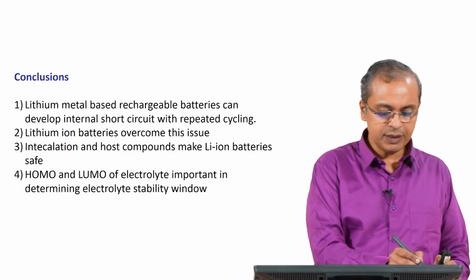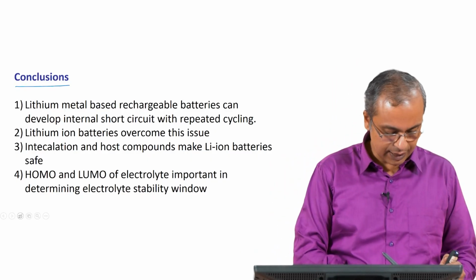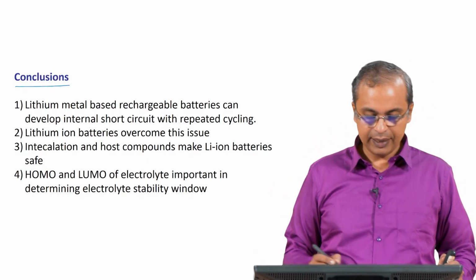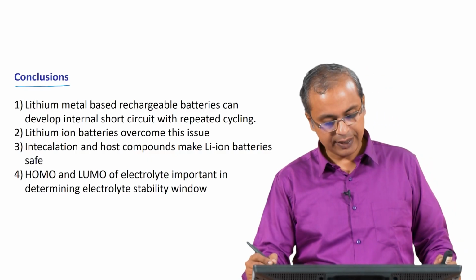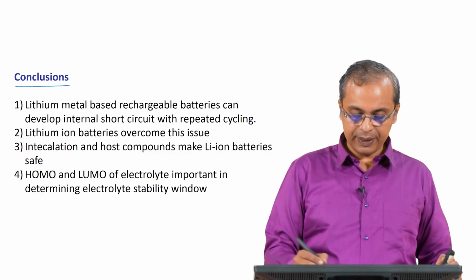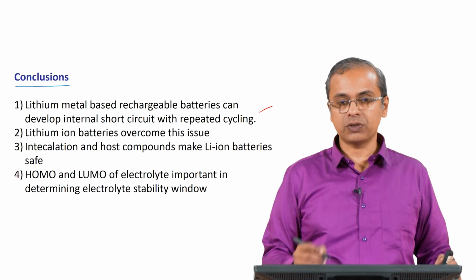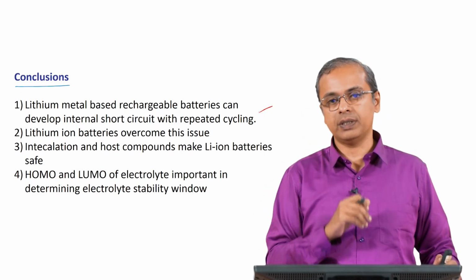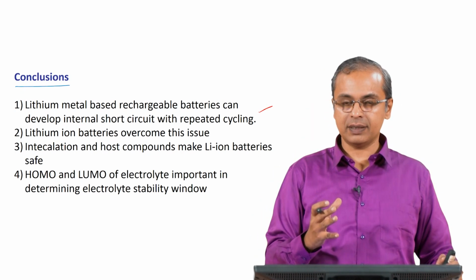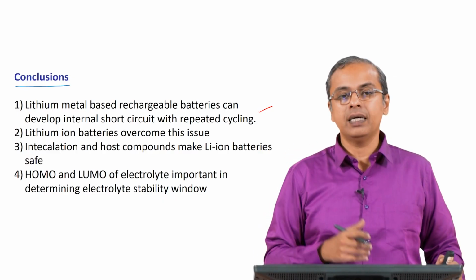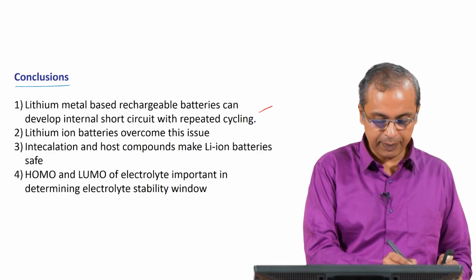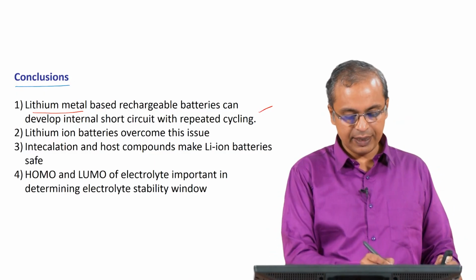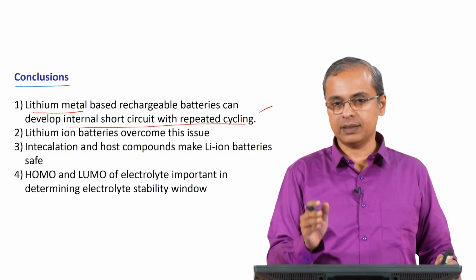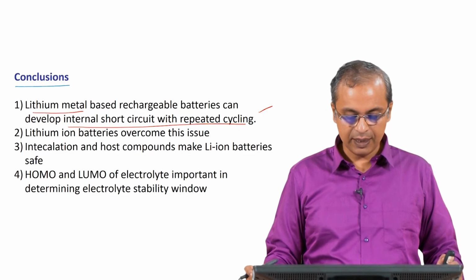So, in terms of conclusions, our main conclusions are that the lithium metal based rechargeable batteries can develop internal short circuit with repeated cycling. So, we saw first of all that there are huge advantages to using the lithium metal based battery system, and that is why there is so much interest in it. But we also noted that if you use lithium metal as the anode, then you can have internal short circuit with repeated cycling, and that is not a desirable situation to have.